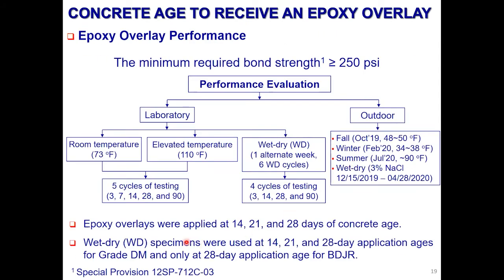The concrete age at the time of overlay application was 14, 21, and 28 days, because typically we had to wait a minimum of 28 days. So we used 28-day performance as the benchmark. But then we compare the performance when we apply overlay at 14 days of concrete age and 21 days of concrete age to see if there's a performance difference.